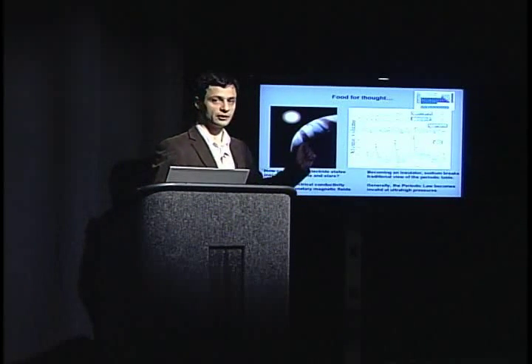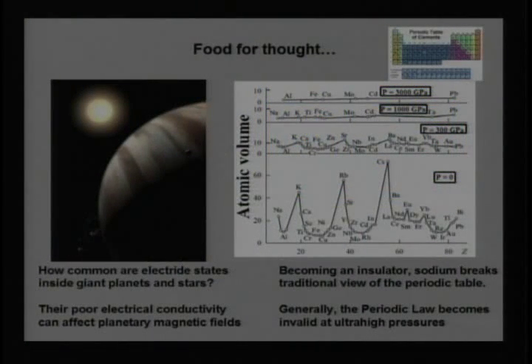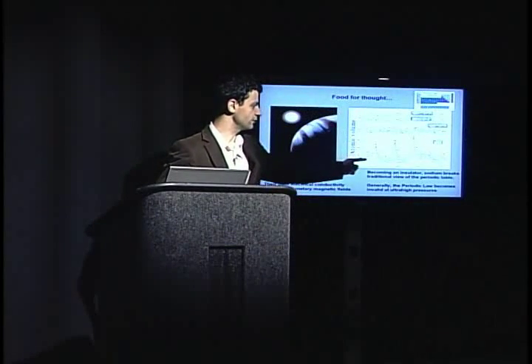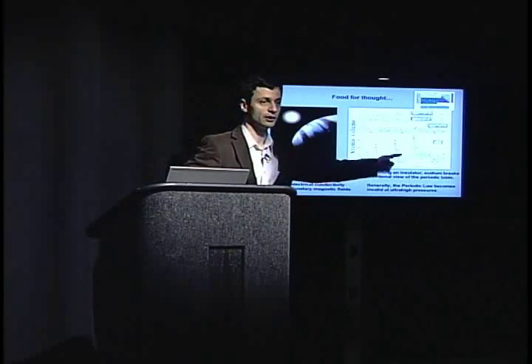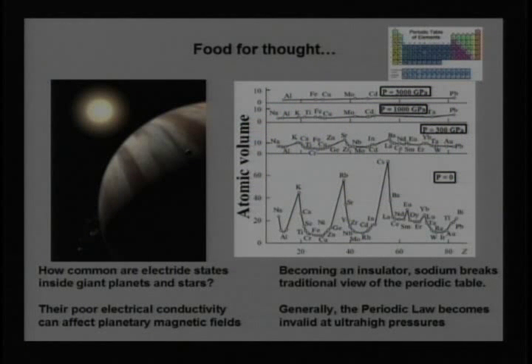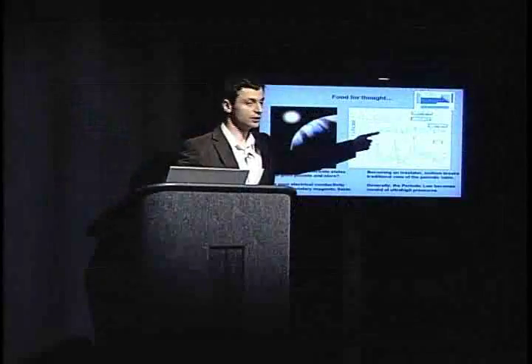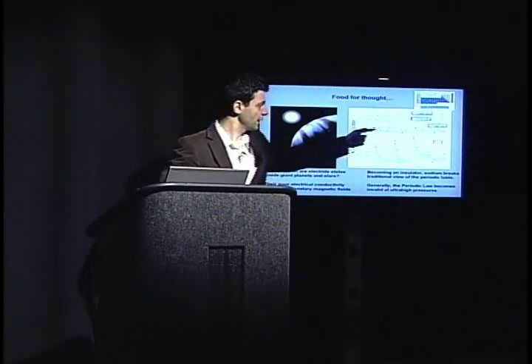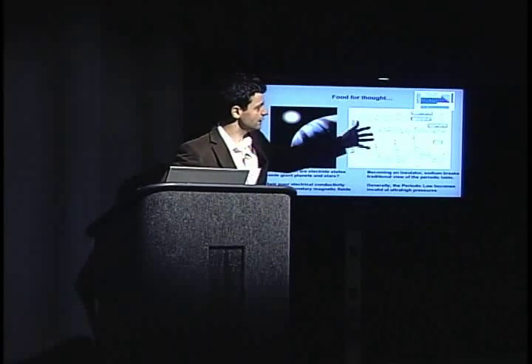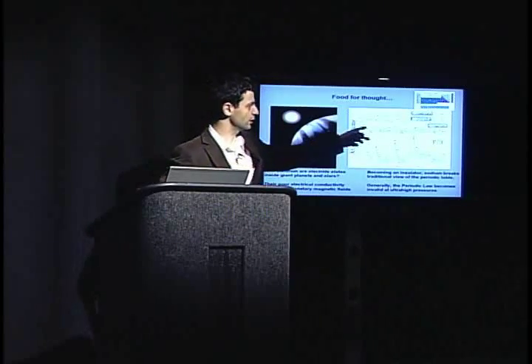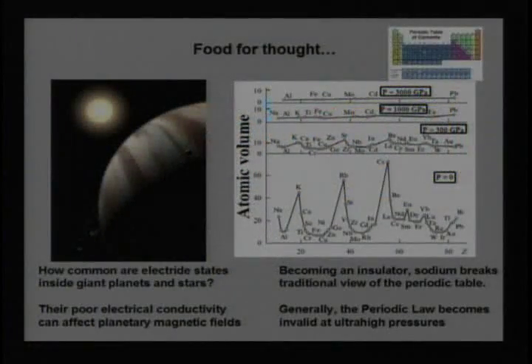This is a beautiful picture that was prepared a couple of decades ago by my Russian colleagues on the basis of their experiments. Look here. At ambient conditions, at very low pressures, such as one atmosphere or zero atmospheres, we have this beautiful periodic dependence of the atomic volume on the atomic number. And this periodic dependence of atomic volume actually is one of the bases of the periodic law. As you increase pressure to 3 million atmospheres, or 300 gigapascals, you can see the same periodic dependence, but strongly dampened. And you can see that this periodicity is really not as manifest as before. And if you increase pressure to 10 million atmospheres, any periodicity disappears.